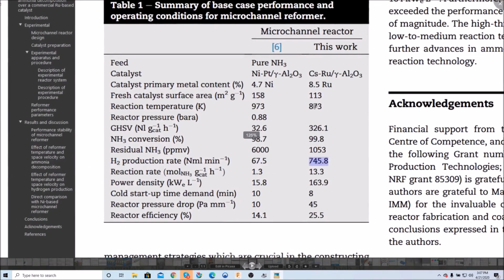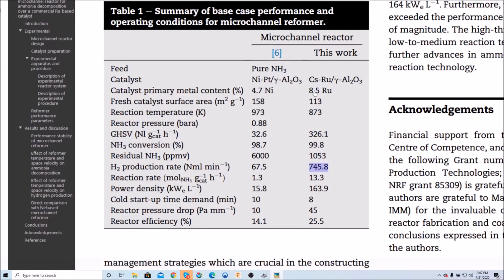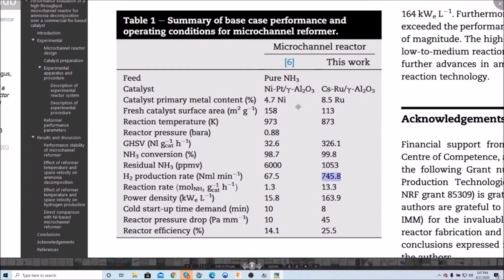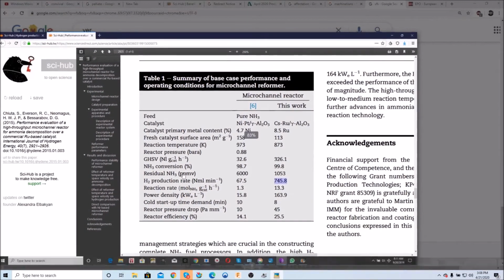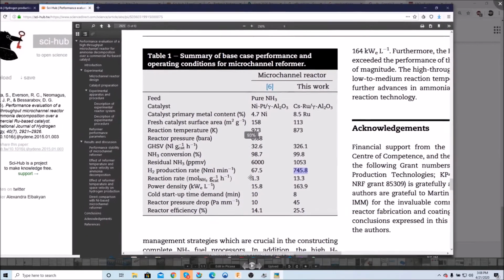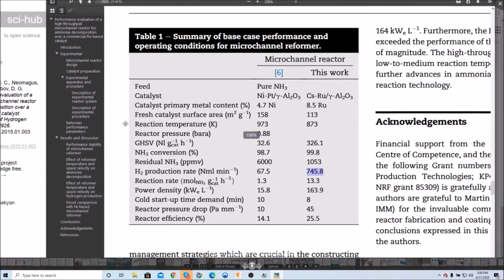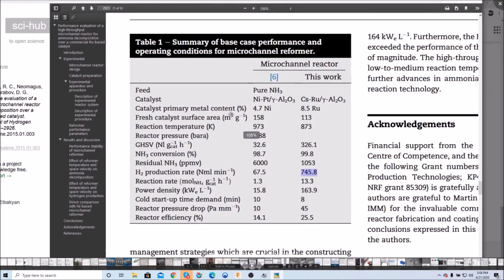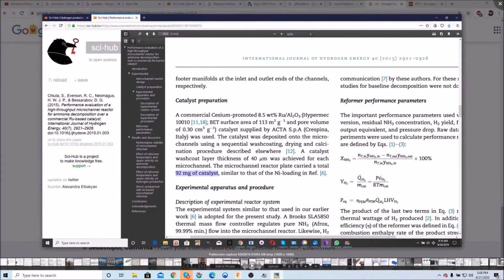So here is a comparison of a nickel versus ruthenium cesium catalyst reactor. And so you can see the difference in the production rate. Very, very significant difference. So around 10 times higher for the ruthenium. Okay, so these are very important numbers.